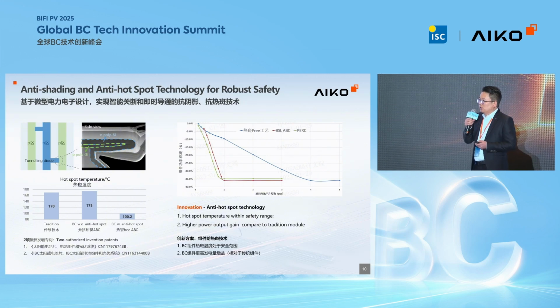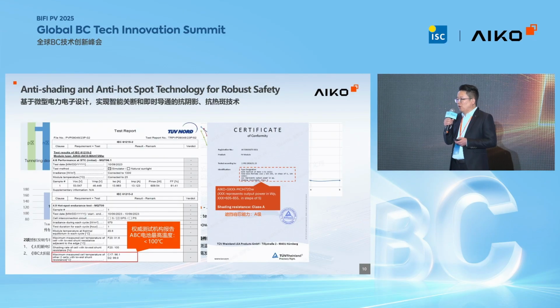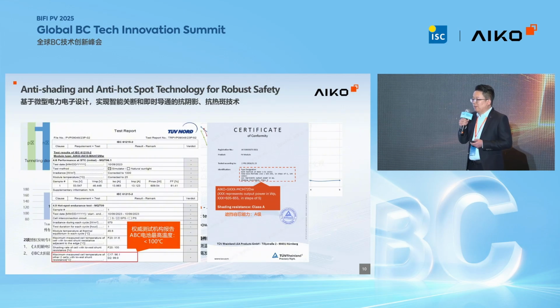So you can see an image of the structure here. The module with such a design shows much lower hotspot temperature and higher tolerance to the shaded cell. Usually, a module without such a structure will lose one-third of its power if one cell is shaded in one string. But for the module with such a design, the shaded cell amount can reach 3 to 4. According to the test report from TUV Nord, the maximum hotspot temperature in the ABC module under shading is below 100 degrees centigrade, and AIKO received the world's first certificate on shading resistance of Class A.